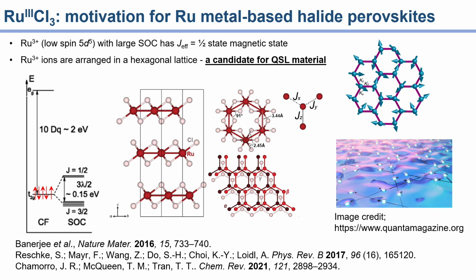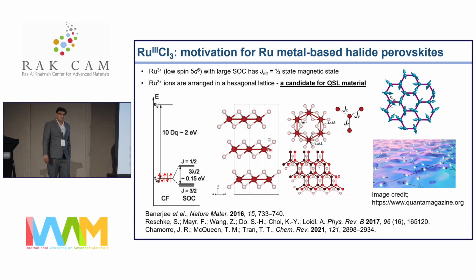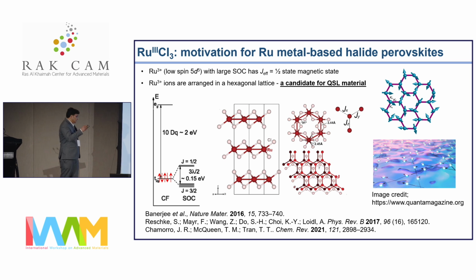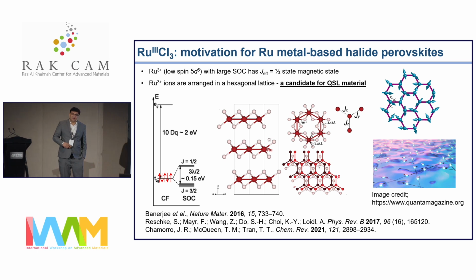a graphene sheet. And as I mentioned here, ruthenium has a high spin orbit coupling strength, because this element belongs to the 4D series, and because of the heavy nucleus, it has a significant influence on electron spin. This particular entanglement we call SOC, and due to it this system is J effective half. This is one of the criteria for selecting a quantum spin liquid material. So the atom should have a spin half system.